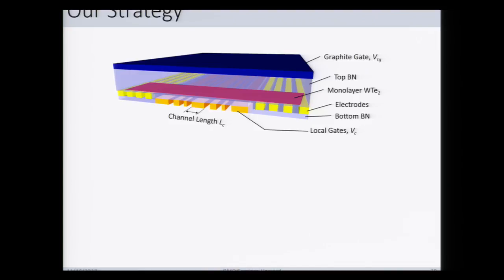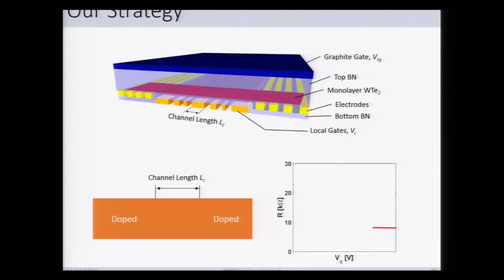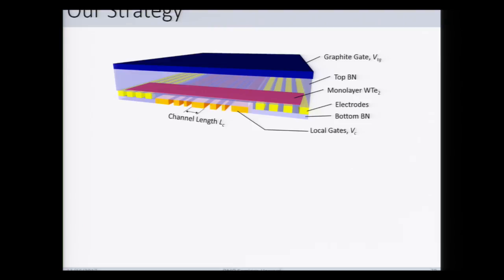We can then place a piece of tungsten ditelluride spanning all of the contacts, and in particular, by touching here, we can make electrical contact to flow current through the device. We have a top layer of boron nitride covering the tungsten telluride everywhere, and additionally, a top layer of graphite that also covers the tungsten telluride everywhere. The key idea here is, one, to dope the tungsten telluride at the contacts to achieve an ohmic contact here, and then separately, the philosophy is that the best way to contact the edge mode is with the two-dimensional conduction band states of the tungsten telluride itself.